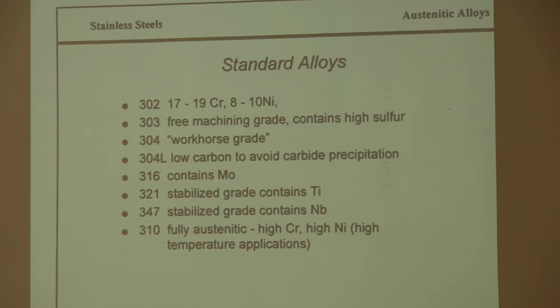The workhorse grade, or the one that you would probably see used the most, it's the most economical of the austenitic alloys, is 304. Oftentimes you'll also hear about a 304L, which is a low carbon version of the 304 stainless steel. There's a wide variety of austenitic stainless steels, but like I said, they are the most commonly used. 304 is kind of the centerpiece alloy, and it's the most commonly selected austenitic grade as well. 316 is probably the next most used, and it substitutes a little bit of molybdenum for the nickel. You have a question?